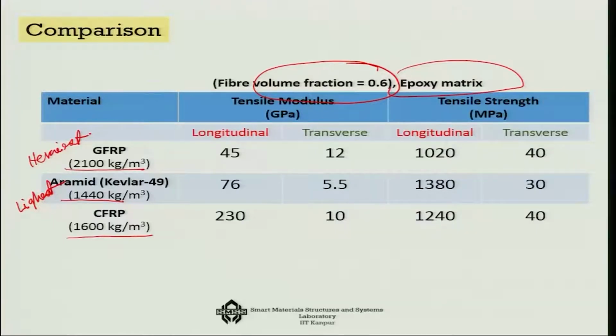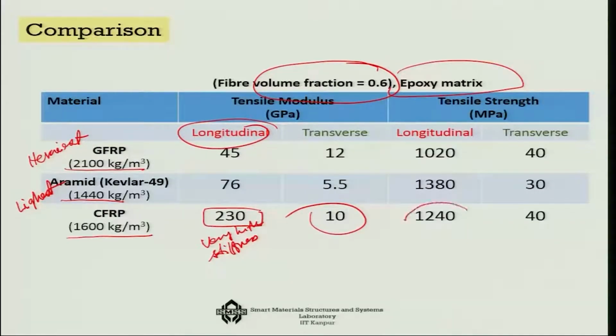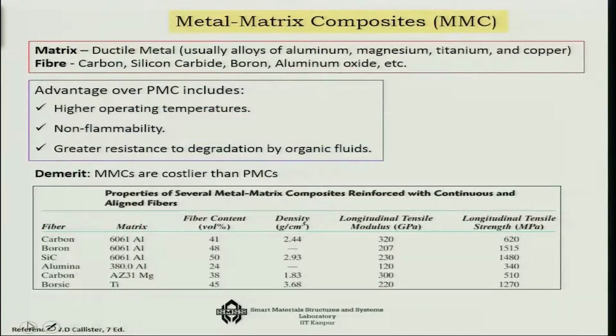And if you look at it from the stiffness point of view, then CFRP is very stiff. Very high stiffness, in fact close to steel, somewhat more than steel in the longitudinal direction. In the transverse direction it is only 10, and tensile strength wise it is close to steel, that is 1240 megapascal, whereas transverse it is about 40. So in many senses, other than the density, CFRP is better because it has higher modulus of elasticity and higher strength in comparison to the other two materials which are mostly used.